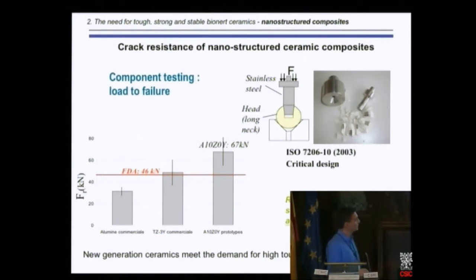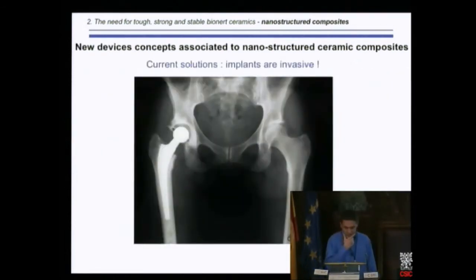And I would say that for these two composites, no decrease of strength was shown even after 50 hours in autoclave. Believe me, it's about 150 years in vivo, so there's much more than reasonable. So we can go now to new device concepts.